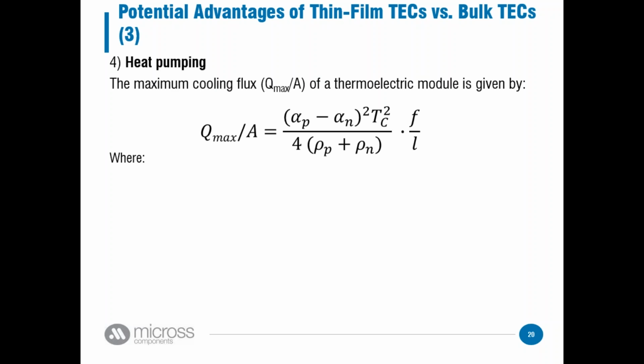For example, you could have your device to be cooled at, say, 10 degrees C. You could have your heat sink at 30 degrees C and still pull heat from the 10 degrees C to the 30 degrees C. That's sort of the magic of what thermoelectric materials can do. So as we talk about this, you can look at this expression here. And of course, we have the Seebeck. We know what the Seebeck coefficient is. We can talk about that up here.